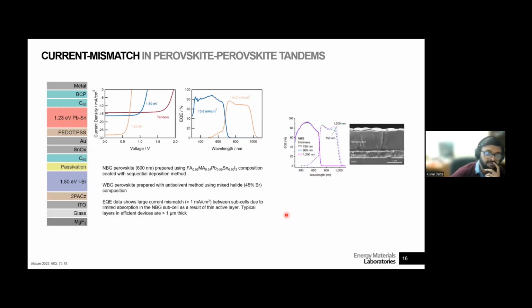Now you run into the same problem here, which is that there's a mismatch in the currents of the two subcells. So if you take a tandem device, that's the schematic here, and then this is the single junction IV of the two cells, and this is the single junction IV of the tandem. And you see that the EQEs show that there's a mismatch of about a milliamp, a bit more even, between the two cells. And that, in our case, primarily stems from the fact that our narrow bandgap cell is quite thin, so it's 600 nanometers, which means that it doesn't absorb a lot in the first pass.